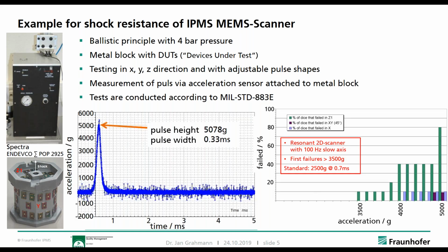So here you see a typical example. We can, for example, apply over 5,000 G to these devices, and the typical pulse width is 0.33 milliseconds. And that pulse width has to be withstood basically by the scanner chips, and we increase it from 1,000, 2,000, 3,000, and so on towards higher pulses in order to determine when the chips eventually break, and that with different designs. And there I brought you an example today on the right side.